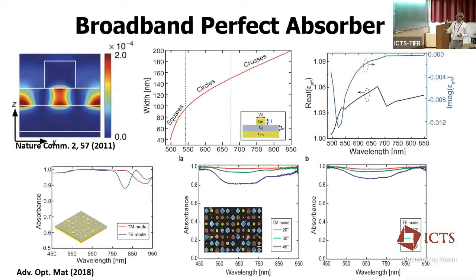One way is, for example, if you want to cover a 500 to 850 nanometer wavelength range, you take different scattering cross sections, different shapes, and you control them in such a way that you put them in a square array, but with randomly distributed scattering elements. Then you see that you get a broadband response. In this case, we showed a broadband perfect absorber. So the geometry is here.